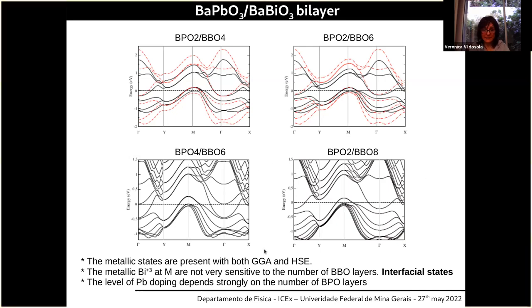So the metallic bismuth 3 plus states at M are not very sensitive to the number of BBO layers, and for the interfacial states, the level of lead doping depends strongly on the number of BPO layers.